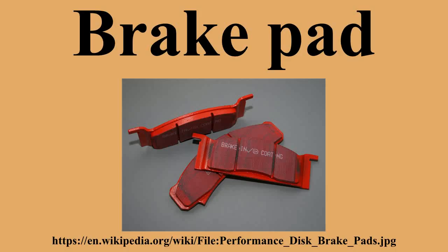Semi-metallic materials, synthetics mixed with some proportion of flake metals. These are harder than non-metallic pads, and are more fade-resistant and longer-lasting, but at the cost of increased wear to the rotor drum, which then must be replaced sooner. They also require more force than non-metallic pads in order to generate braking torque. Fully metallic materials. These pads are used only in racing vehicles, and are composed of sintered steel without any synthetic additives. They are very long-lasting, but require even more force to slow a vehicle and are extremely wearing on rotors. They also tend to be very loud.